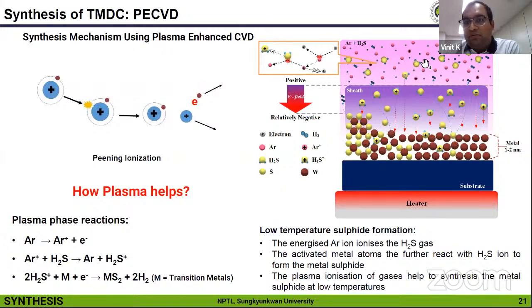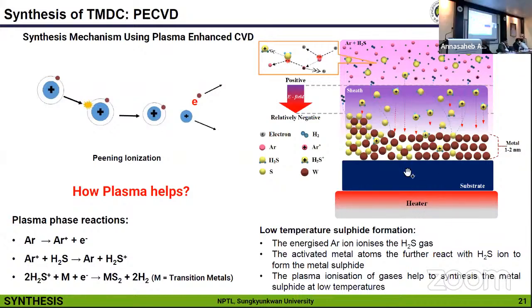As shown in this schematic, we mainly use two gases in this condition, argon and H2S. We use argon because we need more ionization of the gases, and we need H2S because this is the primary gas which combines with our metal. As shown in this figure, these ions charge and recharge repeatedly, and due to the electromagnetic field, the ions bombard our material, and the metal sulfide is formed. While doing this, we can also use a heater or heating material to heat the material to get the appropriate result, whatever we want.